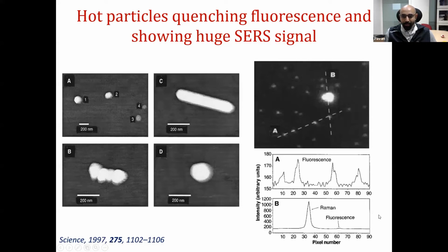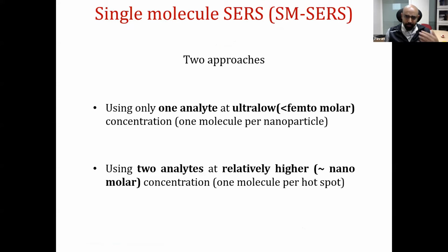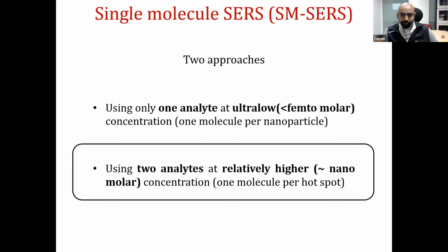This is probably one of the first reports where you find that the fluorescence and the Raman scattering cross sections are inverted. This is spectacular for people who have been doing this kind of spectroscopy, because most of the time it is the other way around. This is one of the first reports where you will find such an inverted process. These two reports gave a lot of confidence that single molecule SERS can indeed be achieved, but it needed further refinement. One of the important refinements was to introduce the so-called bi-analyte technique.